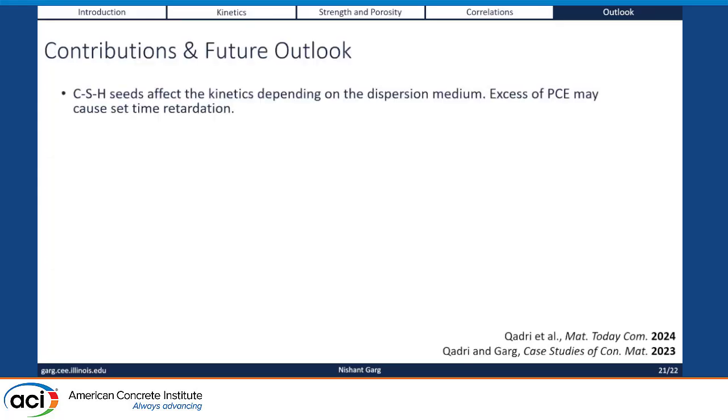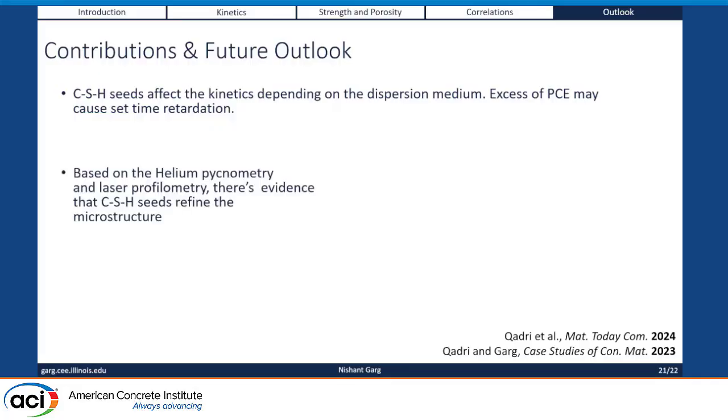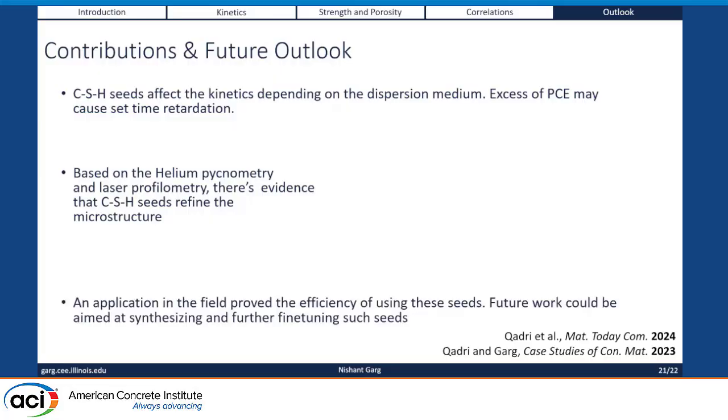So if I were to conclude what we have talked about here, CSH seeds, they affect the kinetics depending on dispersion medium. Excess of PCE may cause some set time retardation. Based on helium pycnometry and laser profilometry, we now do report evidence that CSH seeds actually do refine the microstructure. I think this is very important because now we have an actual impact on durability.